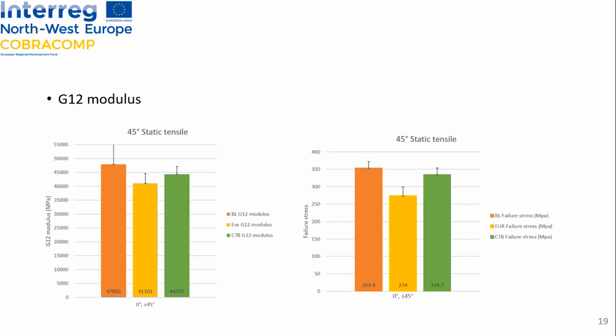For the G12 modulus, it's quite comparable with the three structures. And concerning the failure stress, the interlock braid reaches values closer to the baseline compared with the monoaxial configuration.